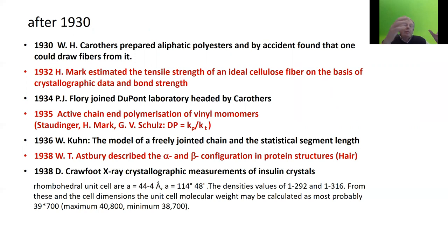But anyway, now the whole field of macromolecules was developed, and suddenly it exploded. In 1930, Carothers prepared the first aliphatic polyesters, so polycondensation polymers. And by accident, he found that one could draw fibers from that. Hermann Mark even estimated the tensile strength of an ideal cellulose fiber on the basis of the crystallographic data and the bond strength. So knowing the size of the unit cells, the number of molecules going through the unit cell, and the bond strengths, you can calculate how strong a fiber could ideally be.